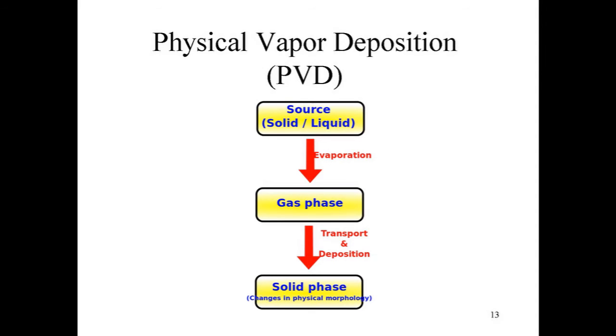After the masking, physical vapor deposition was operated. With this method, source material is heated and its phase is changed to a vapor phase, and then back to a thin film condensed phase in a vacuum atmosphere. Having tested various parameters with spin coating, we passed to the deposition step with the most proper coatings and lifted the mask off from the gold particles.